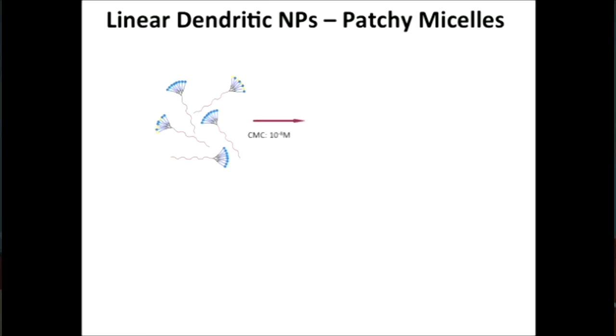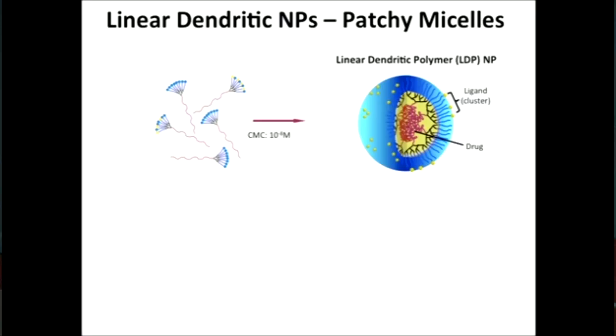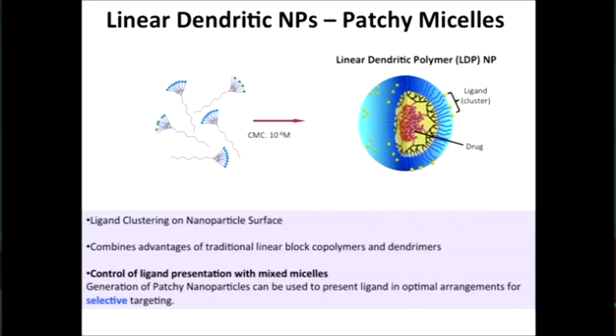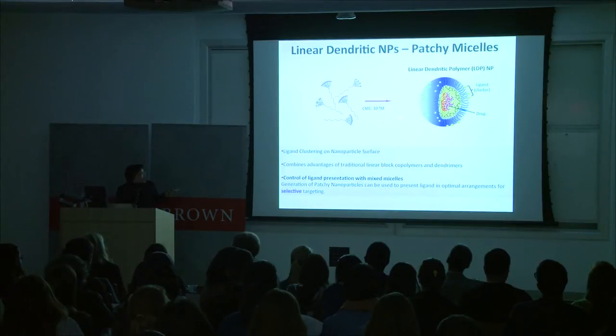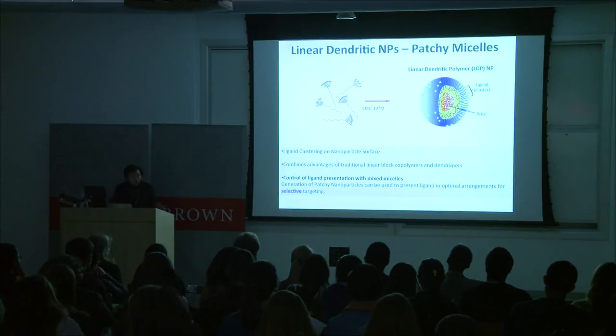So here, what we're showing in this cartoon is that we have polyethylene oxide end groups that have nothing but just a hydroxyl group, which is water soluble at the end, and those are shown in blue. And we can also functionalize them with varying degrees of a ligand. In our case, we chose folic acid, which binds to the folate receptor, which is overexpressed in ovarian cancer cells and a range of other types of cancer cells. And we can then mix them together and produce a self-assembled micelle in which the core can contain drug, but the outer regions have these pre-clustered arrangements already present on their surface. And we can, of course, vary the amount of clustering on the surface in terms of the number of clusters and the size of the cluster. And by controlling this ligand presentation, we can actually generate mixed micelles that can give us selective targeting.